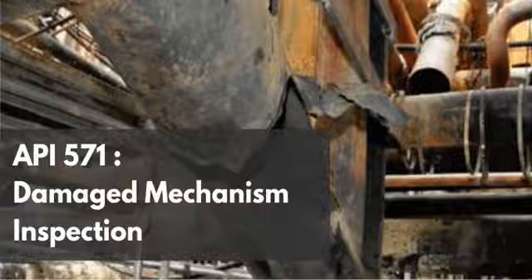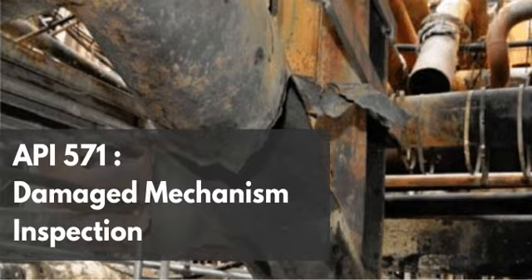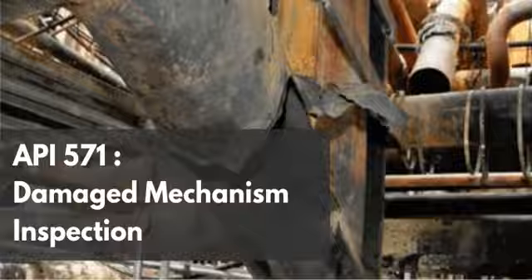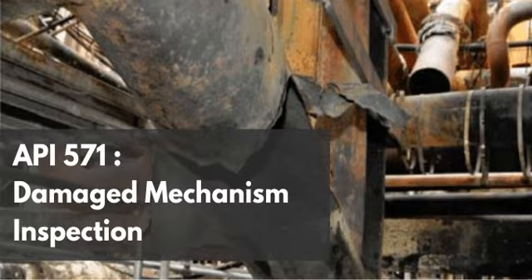You rarely see a massive, high-pressure amine regenerator tower built out of solid 316L stainless steel. The cost would be astronomical. Astronomical. And solid stainless doesn't always provide the heavy structural tensile strength required for massive pressure vessels anyway. That's where roll-bonded or explosively bonded cladding or weld overlay becomes the engineering solution. Exactly. You utilize heavy, thick-walled carbon steel for the pressure boundary, the structural skeleton of the vessel. But you apply a thin, continuous layer of austenitic stainless steel to the internal, process-facing surface. Right. And as long as that clad layer remains intact, acting as an impermeable crystallographic shield, the aggressive amine never touches the susceptible, stressed carbon steel beneath it. So the mechanism is defeated by physical isolation. Defeated before it even starts.